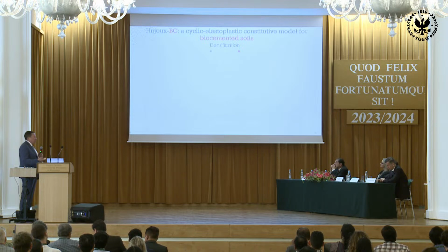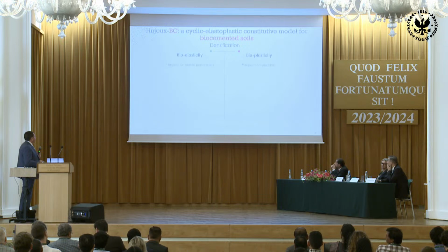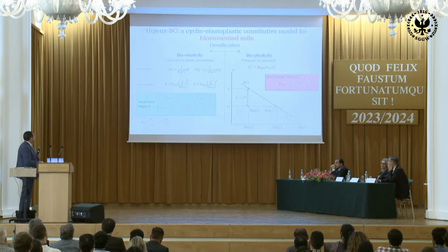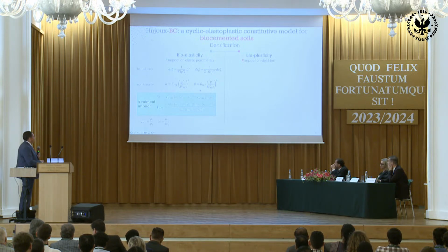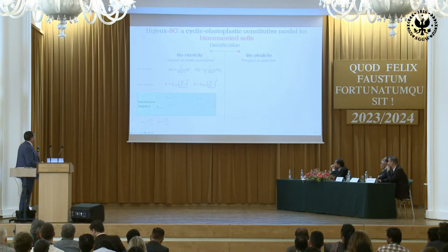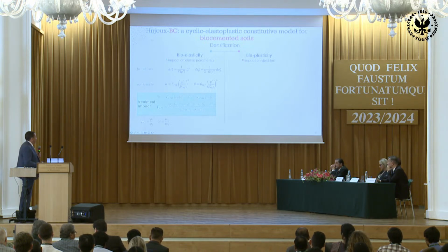In this model, we will now introduce the two processes that I mentioned before. First, densification, so we have to do it in an elastic part and in the plastic part. The elastic part, we do by changing the bulk modulus and the shear modulus, because by this coating of crystal around the grains, we are changing the bulk modulus and shear modulus, and we do it in this mathematical way, where we relate this to the amount of mass that is precipitating in the soil.